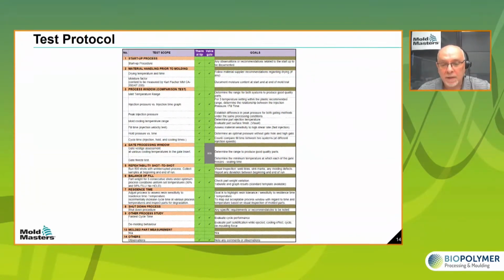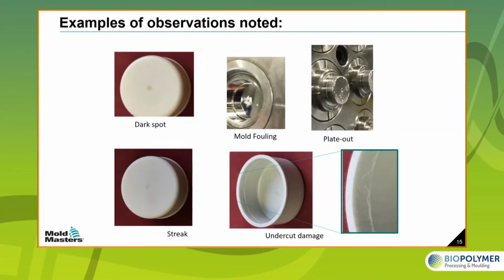We evaluate the residence time by increasing the cycle, by opening the gate and pausing, letting the material sit for 5 minutes and then molding again to see if there's any degradation observed in the molded parts. Of course, we're interested in the gate quality. Anything that we observe, we make note of, so that a molder molding that material isn't starting from ground zero. They have the benefit of our experience. Any observations will be shared. So during our testing, any observations that we might make will be noted.